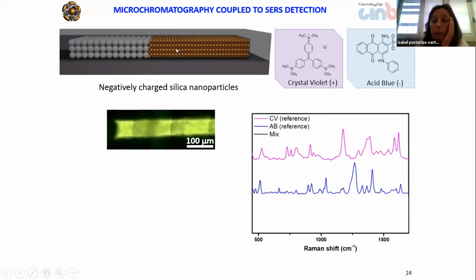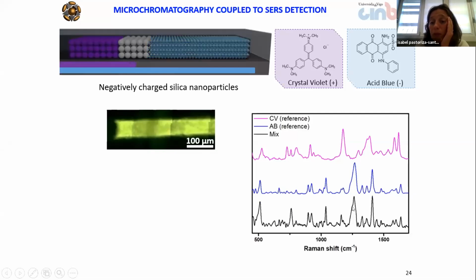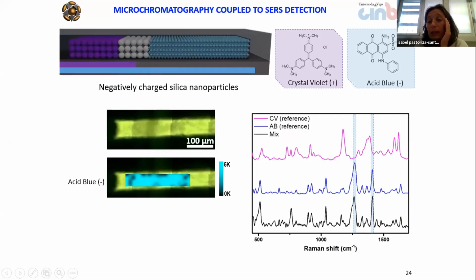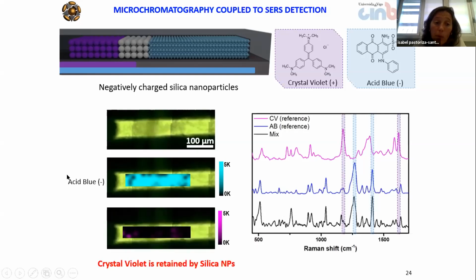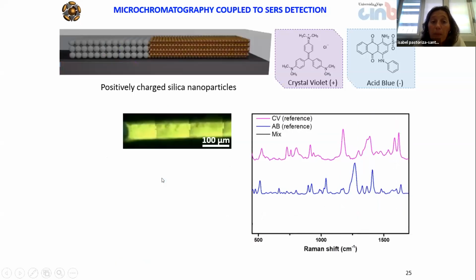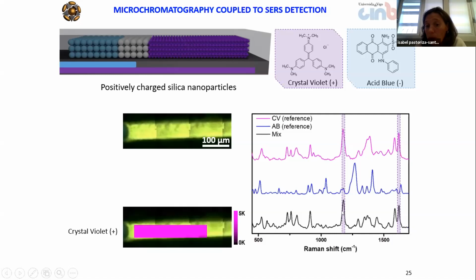And when we introduce them as a mixture in the microfluidic channel, here is the resulting spectra, and we observe just the signals corresponding to the acid blue, because the crystal violet, since it is positively charged, is retained on the silica particles that are negative. This was also checked by SERS intensity maps, where we can only observe the acid blue on the plasmonic supercrystal region. But the nice thing is that we can do the opposite. We can detect the crystal violet instead of the acid blue by tuning the charge of the silica. In that case, this is the resulting spectrum where we can observe the characteristic peaks from crystal violet.